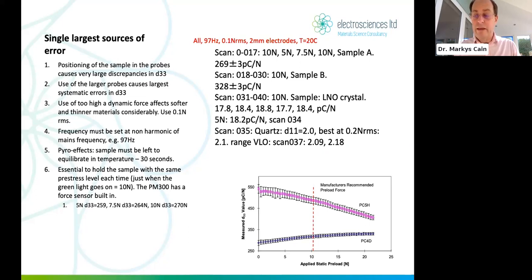So if you have a piece of PZT, which is pyroelectric, and you blow on it, there's a sudden change in temperature, and it generates charge. And when you're measuring charge in the piezo test meter, the meter doesn't know, it doesn't care where the charge comes from. It just measures charge. It doesn't care where it comes from, whether it's piezoelectric force induced or pyroelectric delta T induced.